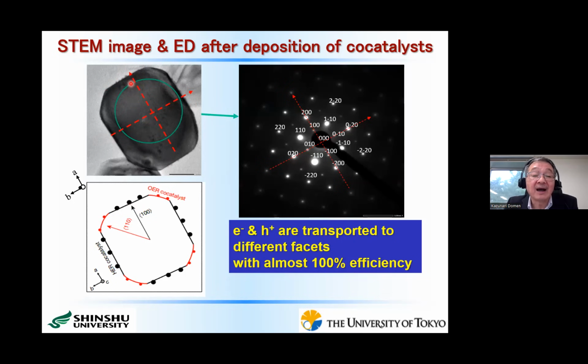And these particles are actually only the hydrogen evolution co-catalyst, the rhodium and chromium co-catalyst. And there exist some other somewhat curved facets, as shown here. On these facets, it is a little bit difficult to identify, but let me say that this is the 110 facet for simplicity. And on this 110 facet, we observed only cobalt oxide, the O2 evolution co-catalyst. That means that the photoexcited electrons and holes are transported to different facets with almost 100% efficiency. So the question is, what is the driving force?